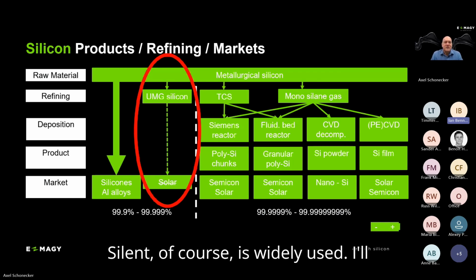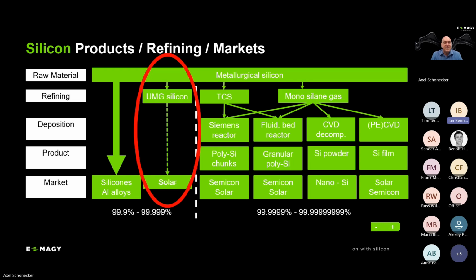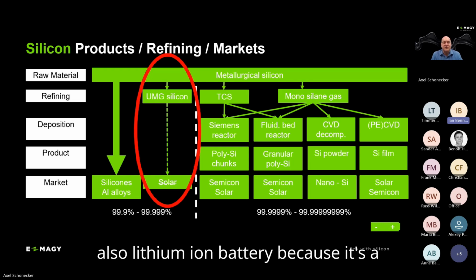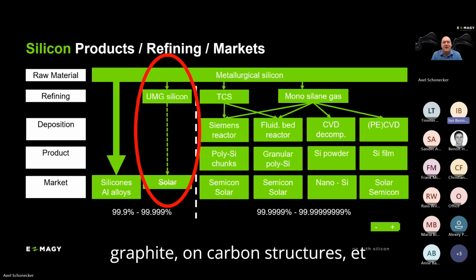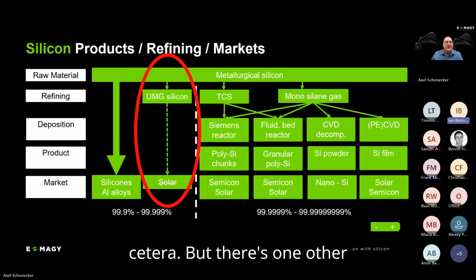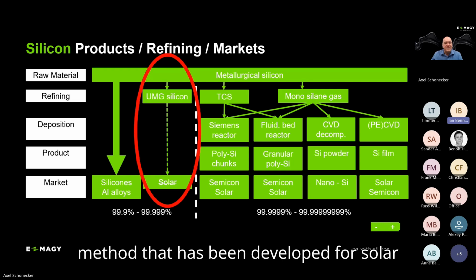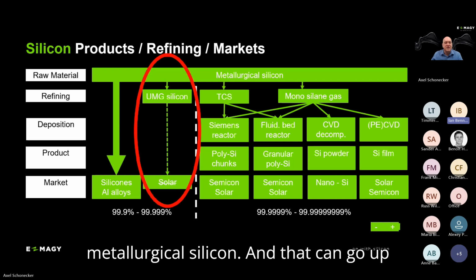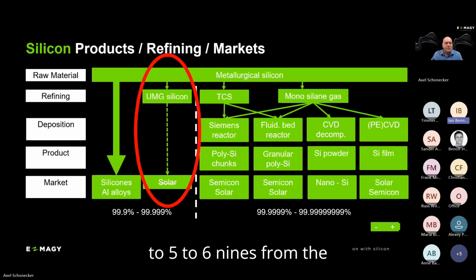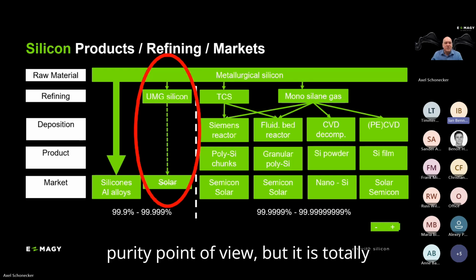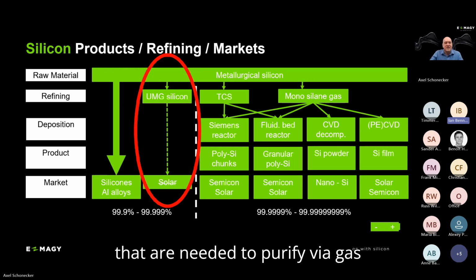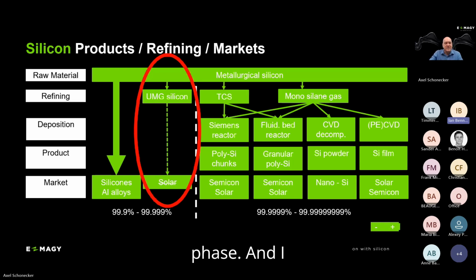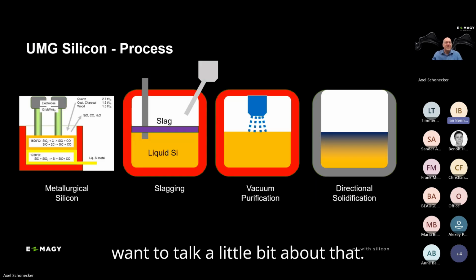Silane, of course, is widely used. I'll come back to that in the lithium-ion battery also, because it's a versatile gas. You can deposit on graphite, on carbon structures, etc. But there's one other method that has been developed for solar in the past, and it's upgraded metallurgical silicon. And that can go up to 5 to 6 nines from the purity point of view, but it is totally different from the chemical reactions that are needed to purify via gas phase. And I want to talk a little bit about that.